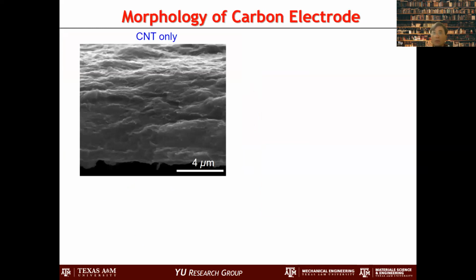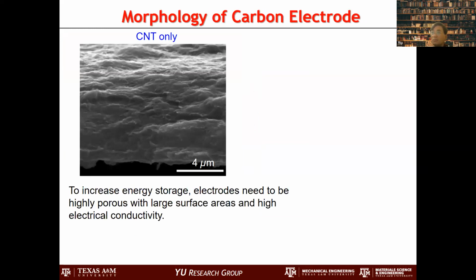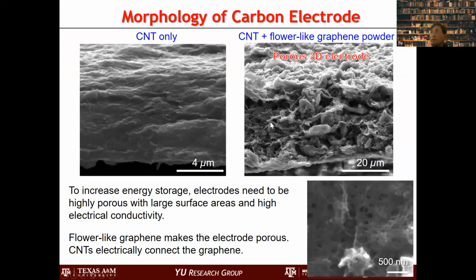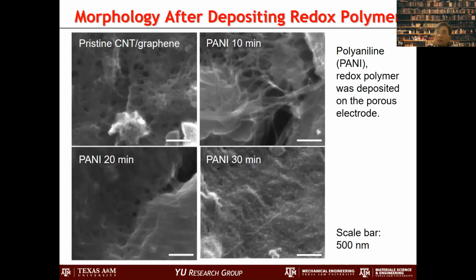So this is a carbon nanotube only electrode, and this is when we actually mix with the graphene flower, and it becomes very porous. Since it's a capacitor, we need to make the electrode porous so that we can have a large surface area, and then we can incorporate this polyaniline. We actually use electrodeposition to make a very thin film of polyaniline on top of that. So that's basically what we have in terms of electrode and in terms of device.